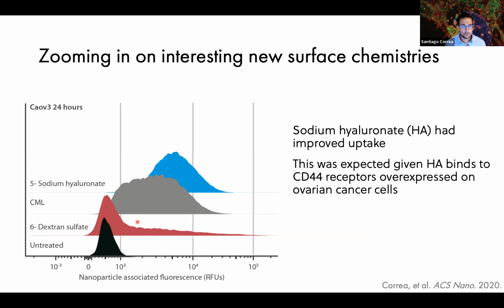Here, for example, is the LBL nanoparticle coated with sodium hyaluronate. This is that tumor targeting carboxylated formulation that I mentioned before. We see that the entire distribution shifts over to the right, and we have a nice normal distribution. We're seeing essentially all the cells are taking up nanoparticles to some degree. And we're seeing in general that uptake is fairly uniform.